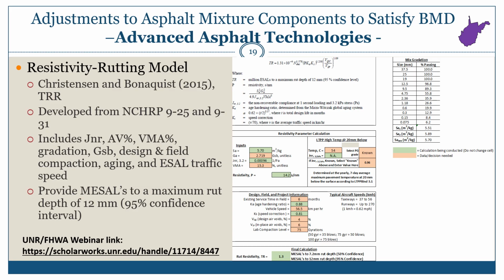It was developed through NCHRP projects 925 and 931. And it includes inputs such as the non-recoverable creep compliance of the asphalt binder, the air voids, the VMA, gradation, bulk gravity, and then also some little aging component depending on the time it was placed and the time that you're evaluating it. All of this provides you with the number of million ESALs to meet a particular rut depth, and that's how it was originally designed. But it could be somewhat calibrated to your performance tests as well, as long as you take that performance test into consideration in the calibration.